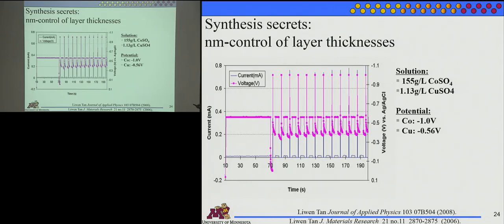So we will get copper at -1, and we're way below its reduction potential. So we have the potential to get, literally, a lot of copper in our cobalt. But if you have 100 times less copper in your pores, when you jump up here to 1 volt to deposit cobalt, it's actually diffusion limited. You get a little bit of copper in your cobalt, and then there's not any more copper ions in your nanopore, so you don't get too much copper there because there's not much in the bath.